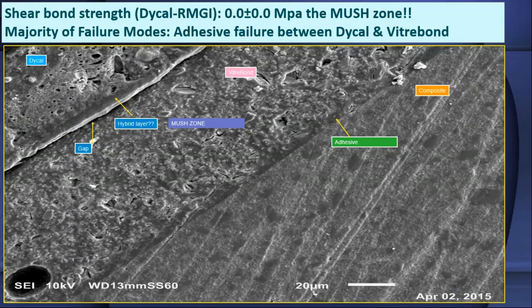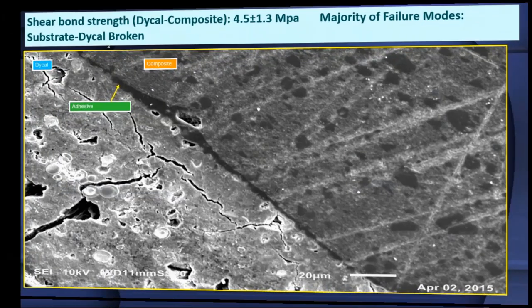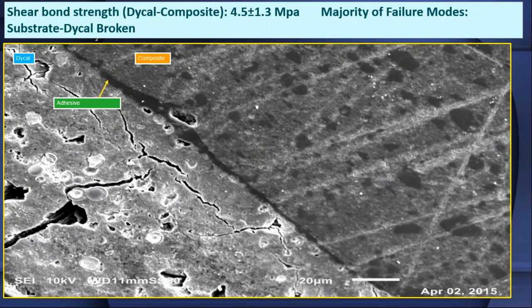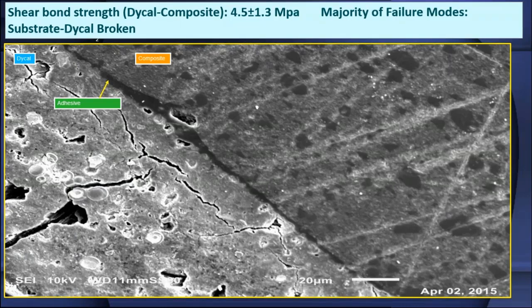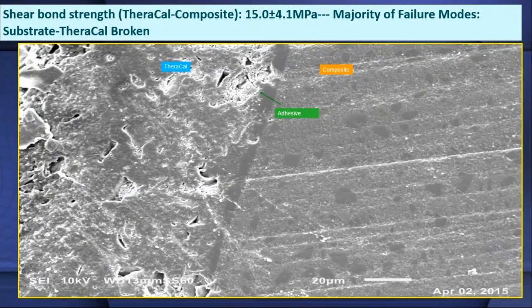So that's like, wow, double whammy. You always have a gap. You always have no bond strength there. You always have leakage there, period. Now, if you put the composite directly on top of the Dycal and cure it, the Dycal just splits apart, as everyone knows, because the Dycal is so weak, when it polymerizes, it just pulls apart the Dycal. Again, that's a real problem, and everyone knows you can't do that. And that's the reason we developed Theracal LC: it doesn't rip apart.